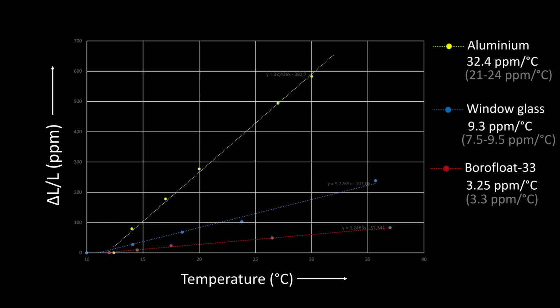Now the next glass is Borofloat 33, which has a well-defined CTE of 3.3 ppm per degree. And here the measured value is actually spot on, with a deviation of less than 2%. So this is a strong indication that our setup and measurement method is not doing a bad job after all. I'm not sure why the aluminum rod I used has such a high expansion. It's an extruded rod, so maybe this created some kind of anisotropy in the expansion.